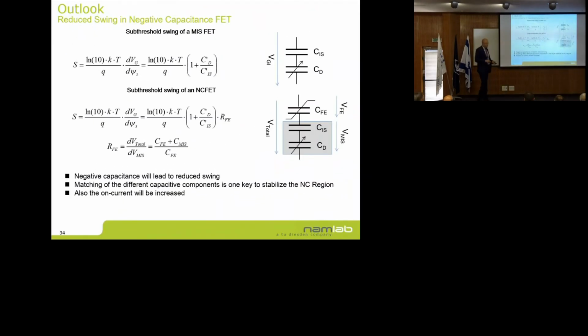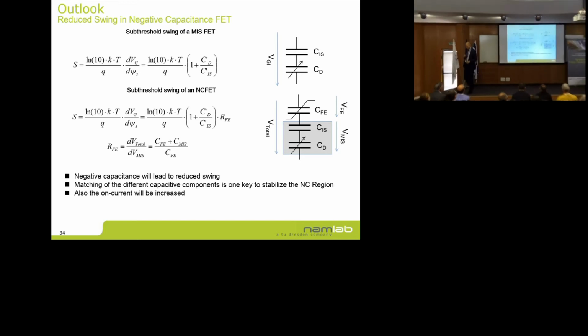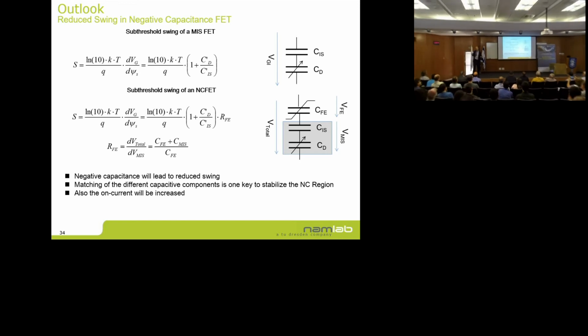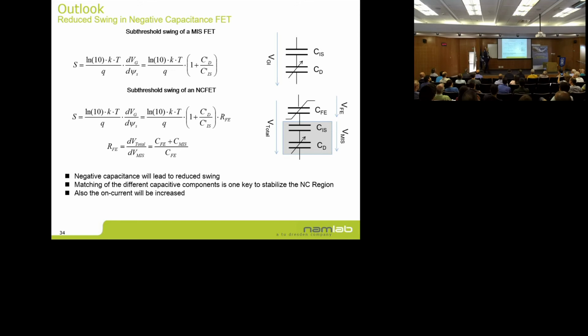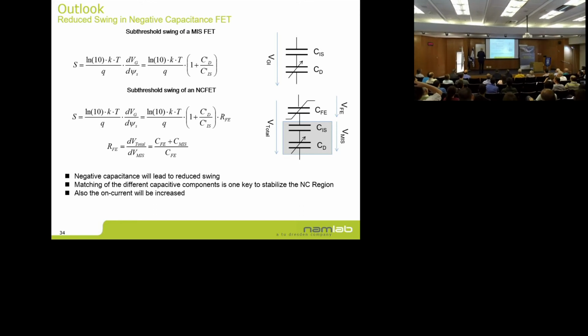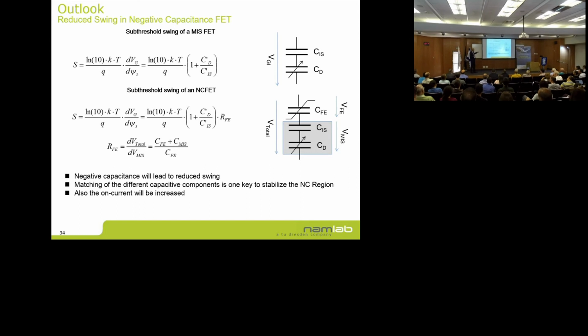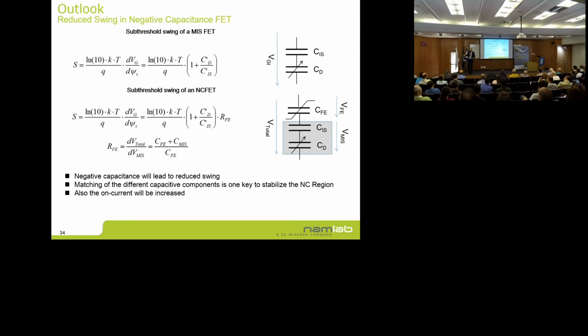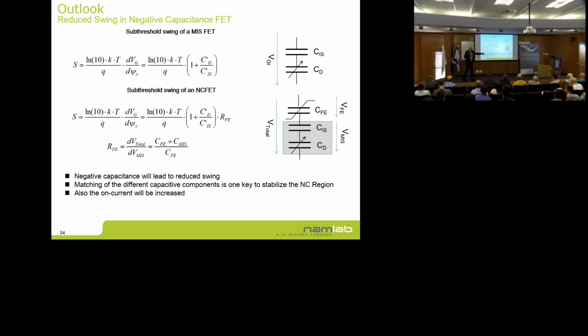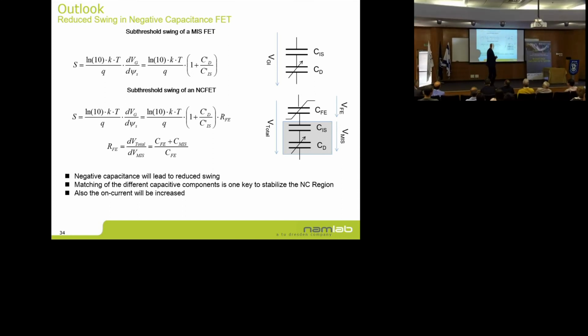And this is the so-called negative capacitance field effect transistor. So many people talk about the so-called Boltzmann tyranny. That means that the subthreshold swing of the transistor is limited to 60 millivolts per decade. And if you go into the equation, you see that typically the depletion layer only makes it worse. You can never get better. Now assume then instead of just having this depletion layer, you have another series capacitance which is negative, then immediately you will get to better values.